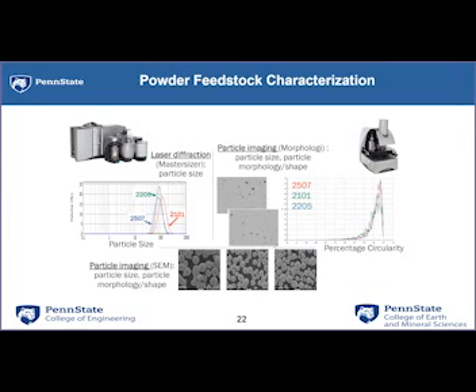We also have been growing in a lot of this powder feedstock characterization. And I will say it's something that I never really thought of before I got into a lot of the metal powders, particularly in the additive manufacturing realm. But we have typically your Mastersizer or your Malvern system for laser diffraction measurement of particle size distribution. We also do a lot with particle imaging and image analysis. And we go a little bit beyond this to allow us to start to get morphologies of powders. But the other area where a lot of these tools are used, and I had never really thought of it, is in the food.